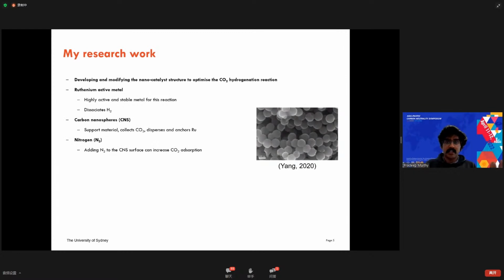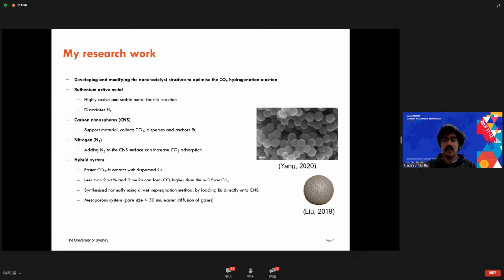The support material is a combination of carbon nanospheres and nitrogen. The nitrogen helps absorb more carbon dioxide over the carbon surface, and the carbon surface itself can also help disperse and anchor the ruthenium over it, thereby reducing deactivation effects, for example by sintering.